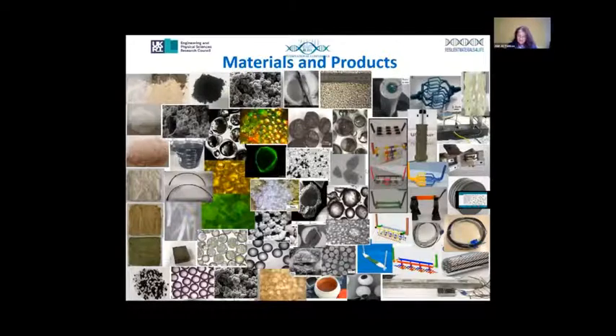For the vascular networks work that Di has already referred to, we mainly use 3D printing of both polymer and cement configurations, and we've explored designs based on Murray's law for flow in blood vessels. Usually for the selection, comparisons and optimizations of cargo, we've tended to start with large glass or 3D printed tubes for ease of fabrication, or just test them in pore solutions. We're also implementing the use of conventional and novel sensors to monitor in situ performance. A focus for us has been on sensors for early age warning of the onset of corrosion.